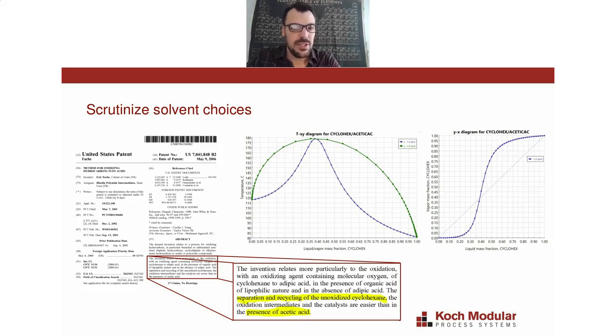In fact, the vapor-liquid equilibrium plots show that we have an azeotrope. On the left, you can see in the TXY plot, we have a maximum boiling azeotrope. And on the right, in the XY plot, you can see the curve passes through the y = x 45-degree line. So this is indicative that there's an azeotrope. And this means if you were trying to recycle unreacted product, cyclohexane, and the concentration of that unreacted cyclohexane were, say, 10 weight%, your distillation tower would produce a pure acetic acid distillate, but a mixture of acetic acid and cyclohexane as the bottoms product, roughly 40% by weight cyclohexane, 60% acetic acid. And that's not usually desirable.